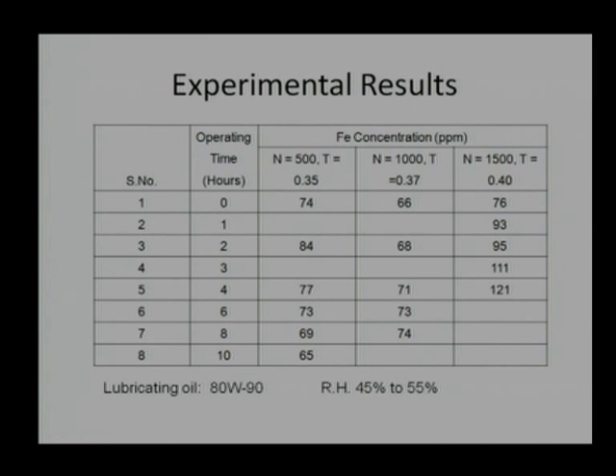If it were the mixed lubrication case, the percentage would not increase, it would come down. So, that is why we feel that this kind of experiment is showing the results related to the boundary lubrication mechanism. Let us see other results. Second set of results: after changing the oil, we have changed the lubricating oil here, so that all the old particles that were getting dumped in the lubricating oil have been removed. Fresh oil, we are getting good readings at 500 rpm.